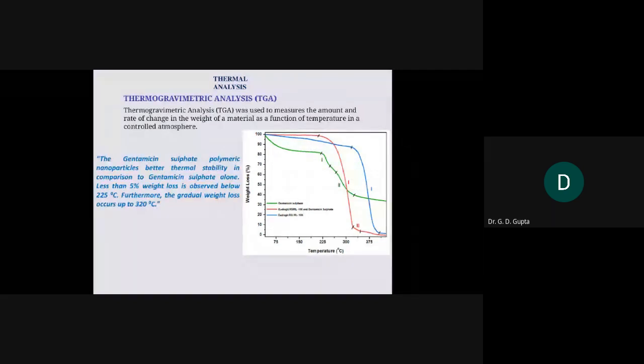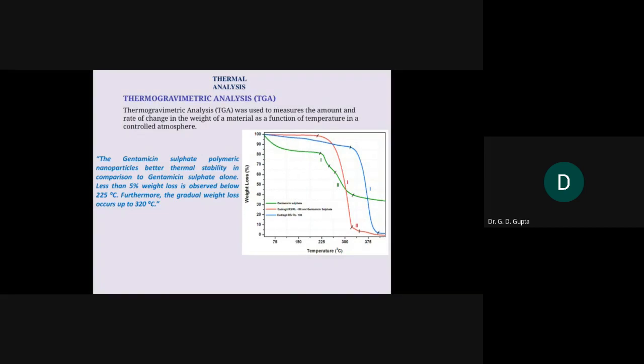Now, you can see that for the gentamicin green line, sharp degradation is observed in 2 phases, near about 230 degrees temperature, and the second one near about 300 degrees. In the blue line, Eudragit, a steady decrease in stability is observed with temperature, while in the case of the nanoparticles, which contain gentamicin and Eudragit, you will find the drug is stable till 225 or 220 degrees centigrade. Although there is a sharp degradation beyond 230 to 240 degrees, we can say in comparison to the pure drug and the pure polymer, our composite is quite stable till 220 degrees centigrade. So that is one of the figures which we have seen in the analysis.